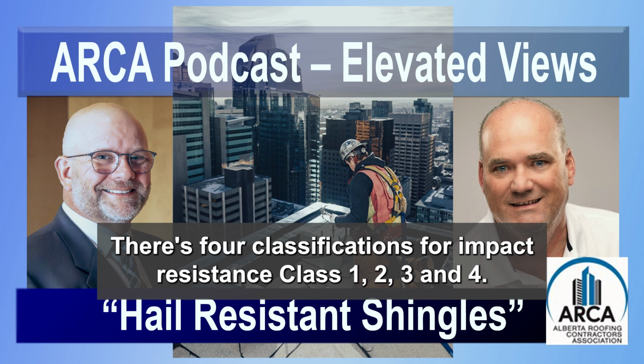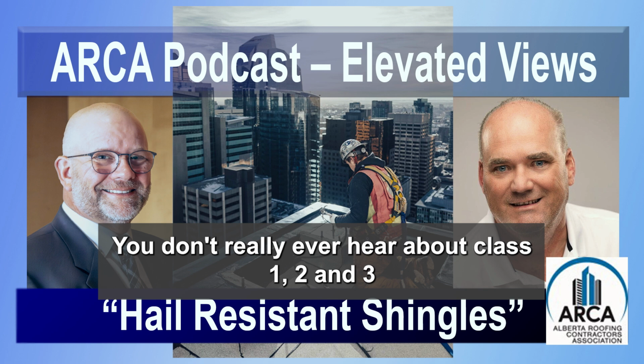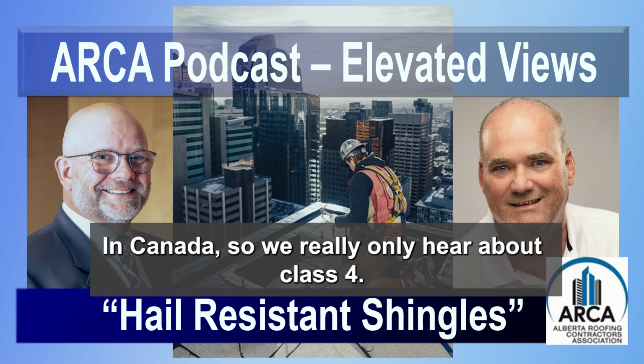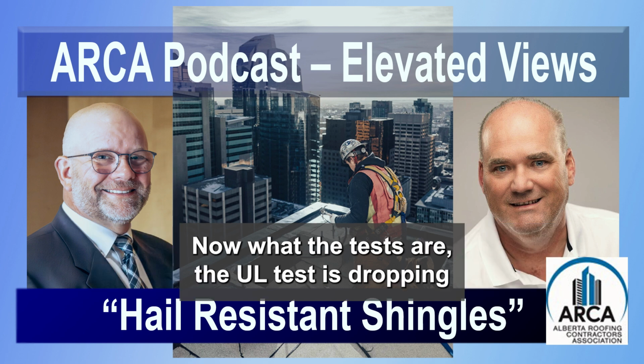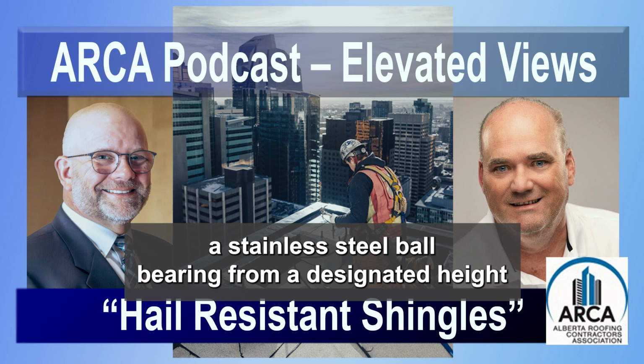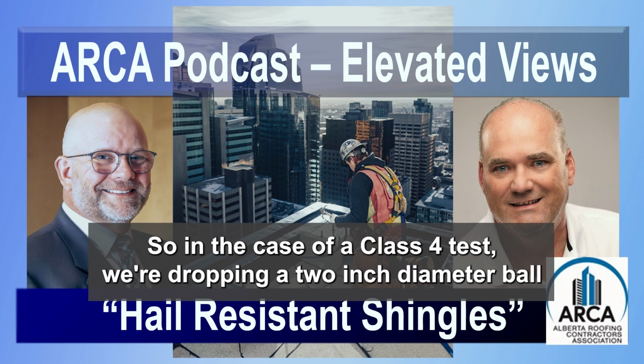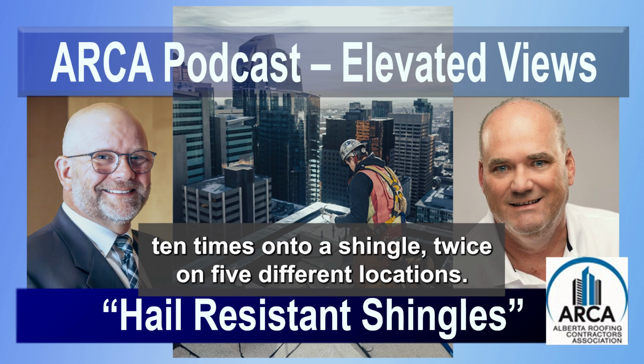There are four classifications for impact resistance: Class 1, 2, 3, and 4. You don't really ever hear about Class 1, 2, and 3 because the insurance companies haven't made them meaningful in Canada. So we really only hear about Class 4. The UL test is dropping a stainless steel ball bearing from a designated height onto a shingled deck and then checking the shingle for damage. In the case of a Class 4 test, we're dropping a 2-inch diameter ball 10 times onto a shingle, twice on 5 different locations.